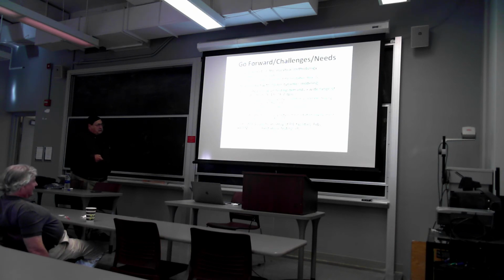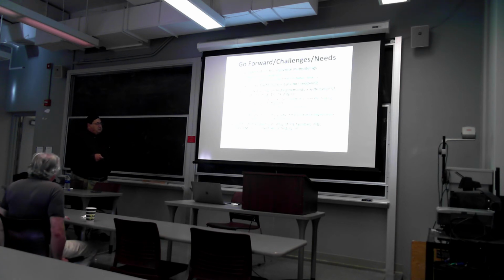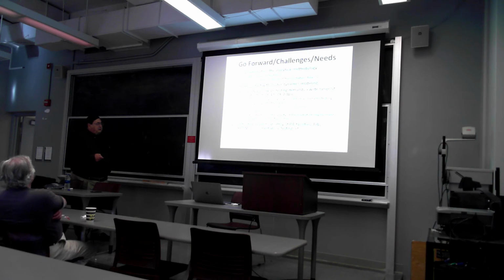So you really have to worry about the quality of the irradiations. And then, of course, as I said at the beginning, at the end of the day, even if you do the irradiations faster, you still have a lot of PIE, and you need dedicated FIBs, high-resolution microscopy, and micromechanical testing to handle all of the specimens that come from doing these experiments at such a high dose, at such a high data rate. There's a large amount of data that usually would take decades to accumulate, which you're now collecting in a period of weeks, and that puts a big stress on your post-irradiation examination.